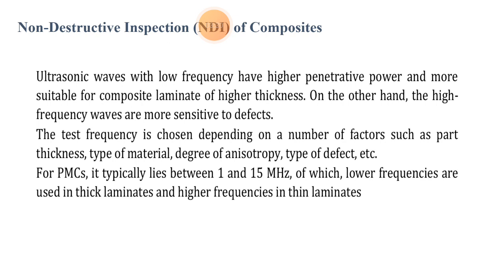Ultrasonic waves with low frequency have higher penetrative power and are more suitable for composite laminates of higher thickness. On the other hand, high frequency waves are more sensitive to defects. The test frequency is chosen depending on factors such as part thickness, type of material, degree of anisotropy, type of defects, etc. For polymer matrix composites (PMC), frequencies typically lie between 1 to 15 MHz, with lower frequencies used in thick laminates and higher frequencies in thin laminates.